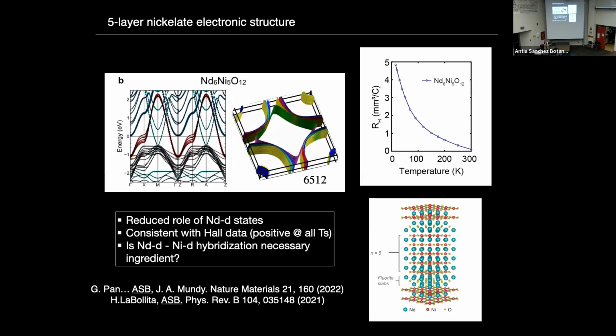But what about the electronic structure, which is what we look into? So for this material, what we have is 5 nickel dx²-y² bands that are the red guys crossing the Fermi level. We have 5 bands because this is the 5-layer material, so you have 5 nickels. We keep on having a certain degree of involvement of rare earth states that are these bluish or turquoise guys. But these pockets are much smaller, so there is a reduced role of the neodymium d states in the material with respect to the infinite layer counterpart. This is once again consistent with the Hall data that is now positive at all temperatures.